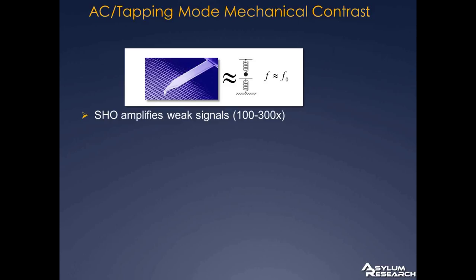One of the nice advantages of this AC or tapping mode is that the simple harmonic oscillator, which I've abbreviated SHO, acts as a filter or sort of an amplifier for weak signals. The quality factor of the cantilever, the oscillator, is typically somewhere between 100 and 300. Effectively, that means we multiply the signal at resonance by a factor of 100 to 300. Also, since it's at fairly high frequencies, we can escape a lot of forms of noise common to experimental apparatus: 1/f noise, building vibrations, acoustic noise, and so on.